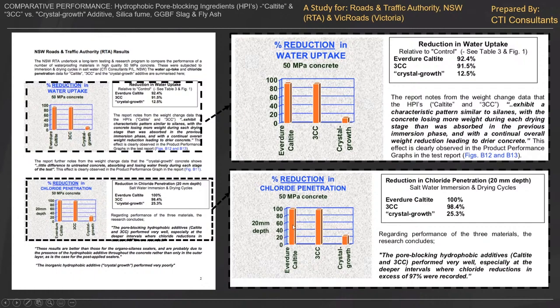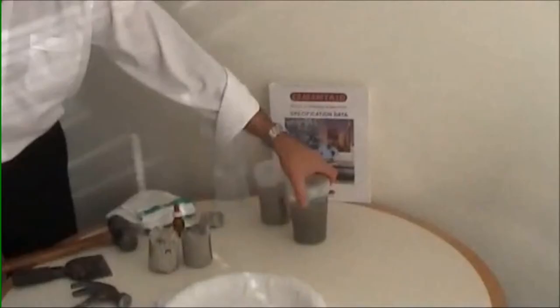Interestingly, they also looked at chloride penetration. You can see here with the full strength HPI, we're getting 100% reduction in chloride penetration and 98.4% with the second product. The crystal growth product does something, but it's 25.3%. That gives you an idea of the measure of improvement you can get with a proper HPI.